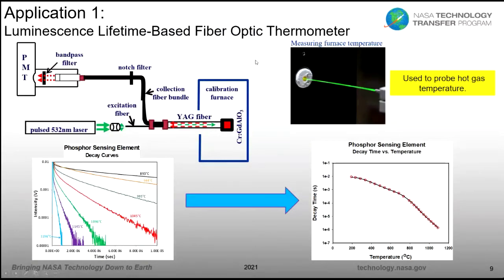Now I'd like to go over several applications that can be implemented with this approach. The first one being the most simple. This will be an implementation of a luminescence lifetime-based fiber optic thermometer that can be used to probe a hot gas temperature. The thermometer itself consists of a YAG optical fiber with a chrome gadolinium aluminate phosphor tip. Through the optical fiber, we can both deliver the excitation light and also collect the emission light. We can do that by using a bifurcated fiber assembly, where through one leg we can deliver the excitation, the pulsed 532 nanometer laser, and through the other leg we can transmit the collected emission through some filtering to a photomultiplier tube, where connected to an oscilloscope, we can watch how the intensity of the emission decays once that excitation pulse has ended.